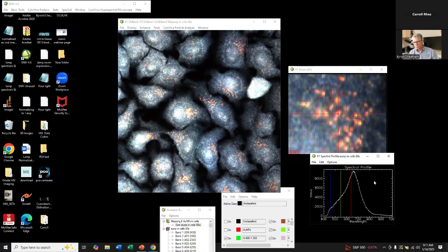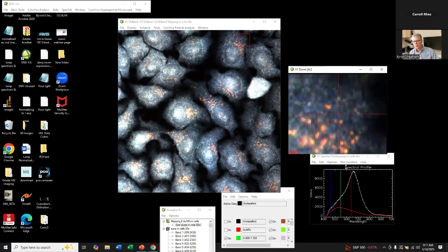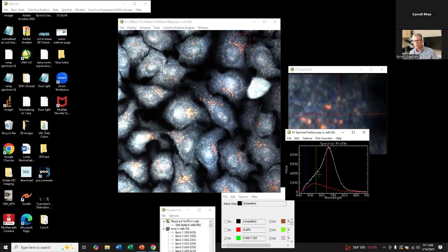If I want to collect spectrum from here, I can collect spectrum. And if I come over to a tissue area where there are no nanoparticles, you can now see I have two spectra. The first is the spectrum of the gold particle in the cell. The second is the spectrum of the cell itself. So you see a couple of things. You see a shift in the spectrum. You see a broadening in the spectrum from the nanoparticle to the cell only. You also see significantly more reflectance spectral intensity being measured of the gold particle, because gold has more spectral reflectance characteristics in its spectrum than the tissue does.